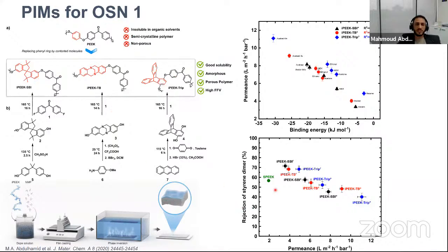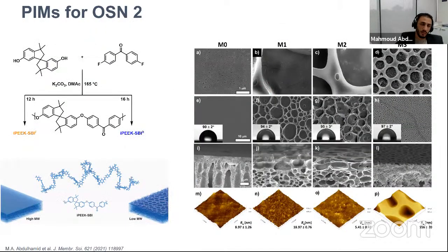The performance of this new generation was way higher than the commercially available one. We were able to fine tune the performance in terms of permeance, going up to 6 times higher than commercially available, while keeping, for some polymers, even higher rejection of styrene dimer. For further investigation, we wanted to see if the molecular weight of this polymer could affect its performance. So we prepared two different molecular weights of polyether ether ketone, and we prepared membranes out of them. The SEM shows very interesting behavior on a polymer that has a low molecular weight. If we have a high molecular weight polymer, the membrane would show just a flat surface, as you can see in this illustration or in this SEM.